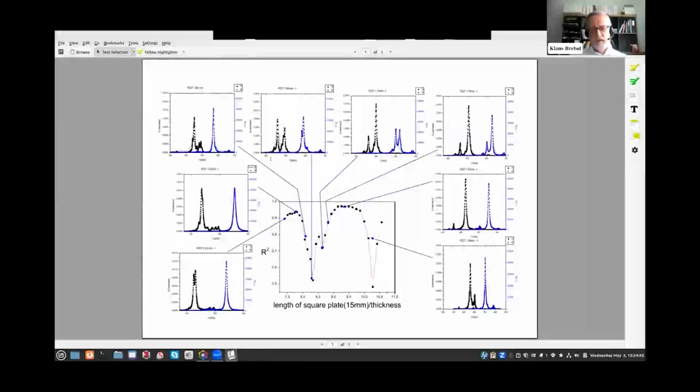If you look at this, here we have the double resonance that was 1.8 millimeter in thickness. If we then thin down the sample, you'll see here at 1.62 millimeters, we have 2 very clean resonances, which we use for extracting the parameter. And the aspect ratio is not 1 in 10 or 1 in 20. It is only 1 in 9. So we have a frequency range which is similar to the one that we plan to use for our modeling.